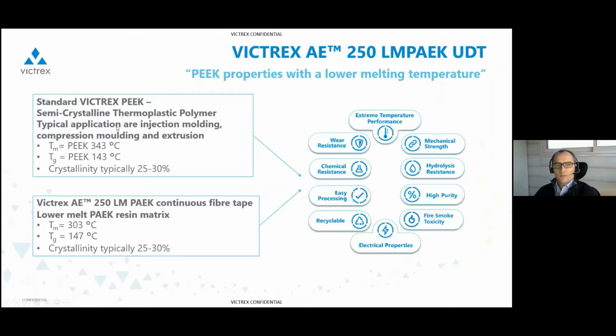But the main difference is what you have here on the left-hand side. The melting point of a standard PEEK is at 343 degrees Celsius. And as you can see here, for low melt PAEK, that's at 303. So we have about 40 degrees Celsius difference. You may think it's not much, but that makes a huge difference in the way of processing these based material forms. In terms of glass temperature, that's about the same, and in terms of crystallinity, that's more or less the same too.